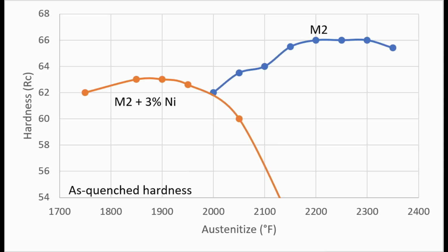Maybe there are certain cases where this could still work. We make sure we're not adding too much nickel. Maybe stick to 1.5% or 1% or 0.75%, I don't know. Especially for steels where we want high toughness. So I think this is an avenue worth exploring for certain steel designs, but given that we've known about the effect of nickel for 100 years and there aren't more steels coming out with it, it's probably not very likely that we're going to see many more.